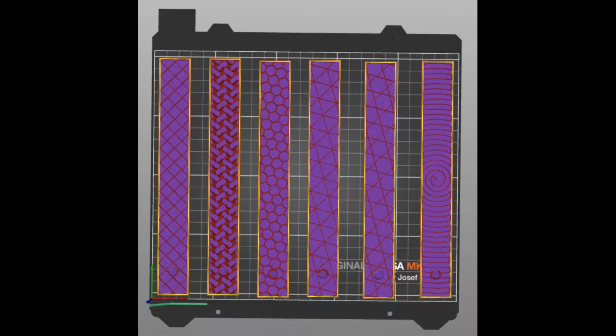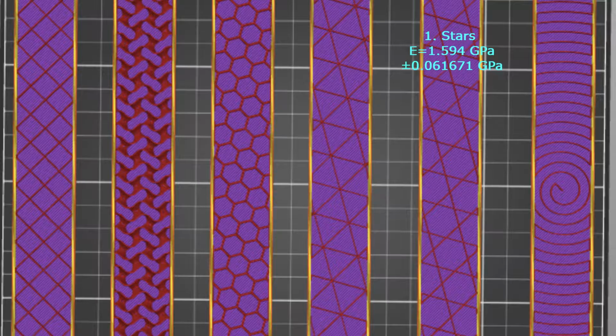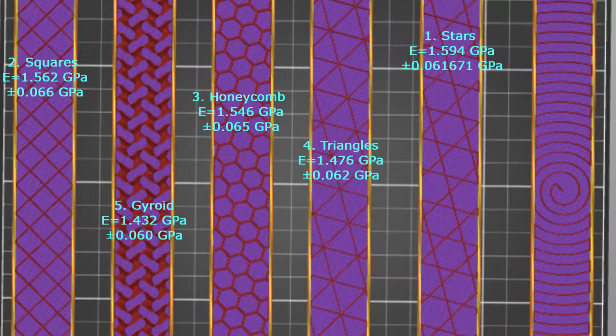In conclusion, the order of strongest designs from greatest to least is stars with a Young's modulus value of 1.594 gigapascals with an uncertainty of 0.061671 gigapascals and a confidence of 95%. The patterns that performed the best in order from greatest to least were squares, honeycomb, triangle, gyroid, then finally Archimedean spiral with a Young's modulus value of 1.2769 gigapascals with an uncertainty of 0.0538 gigapascals and a confidence of 95%.